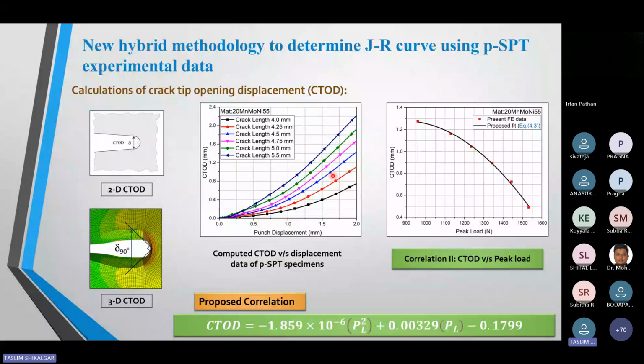The second one is the CTOD, crack tip opening displacement. I want to find out this crack tip opening displacement. This is the methodology available in the literature. Near the crack tip, you need to make a right angle triangle. And where this triangle touches the crack flanks, this distance is known as the CTOD. And this is the 2D methodology. I want to use it in 3D.